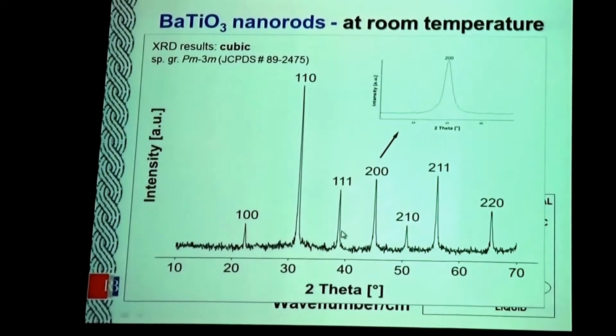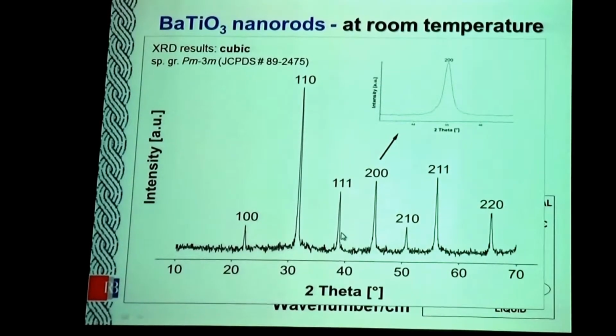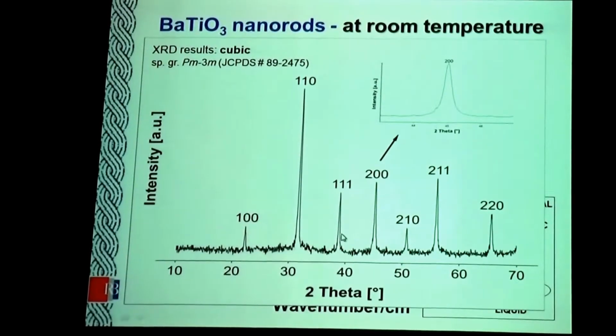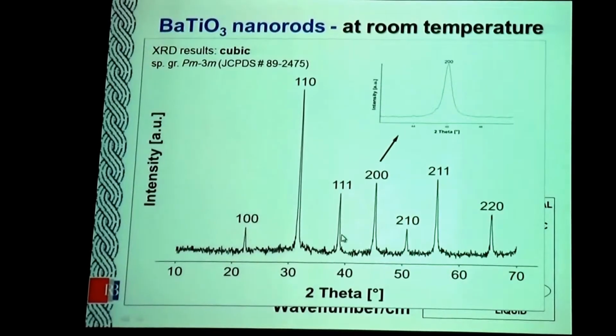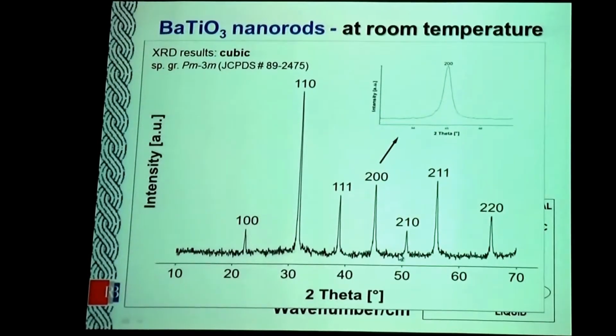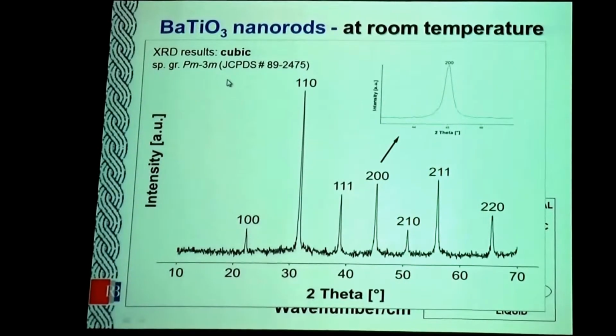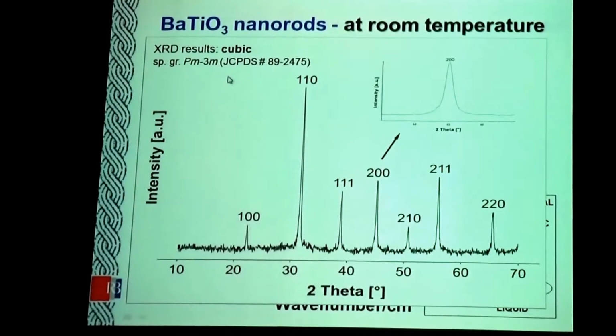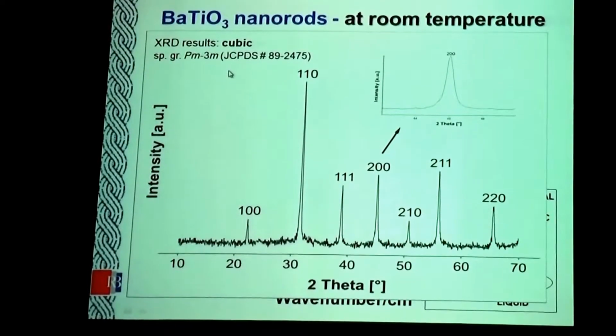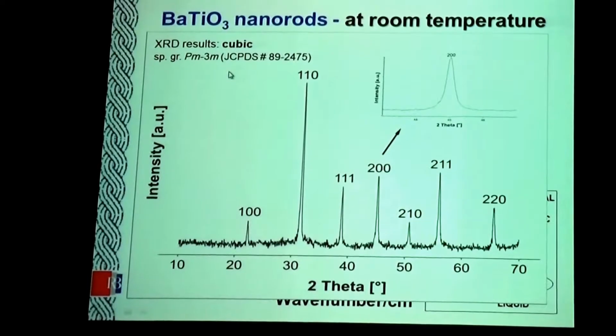However, X-ray diffraction measurements were also done on all the different nanorods, but using X-ray diffraction there was no observation of any tetragonality, and especially they didn't observe a hexagonal structure. There are a few reasons for this.